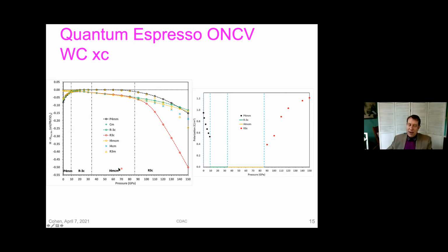And then I4/mcm, I'm going to say more about these, but this is another strontium titanate-like rotated octahedra perovskite with no ferroelectricity. It's a centrosymmetric structure. If we had just quit at 80 GPa or something, then everything would have been clear, and we could have written our paper 15 years ago about absence of ferroelectricity in lead titanate, because this was completely consistent with the experiments, so that we had only the low pressure ferroelectricity and nothing at high pressure.